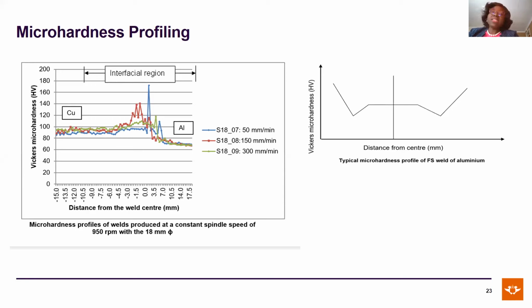But if you look at the microhardness profiling on the left-hand side, this is for aluminum and copper. You will see some peaks at the stir zone, which correlates to the intermetallic compounds that are present in the welds.